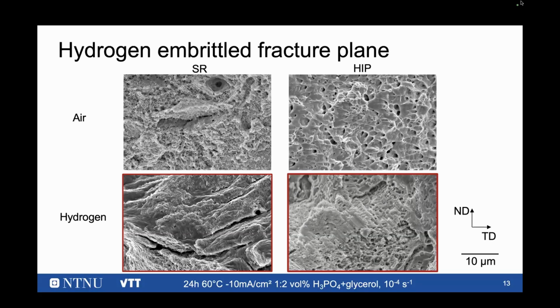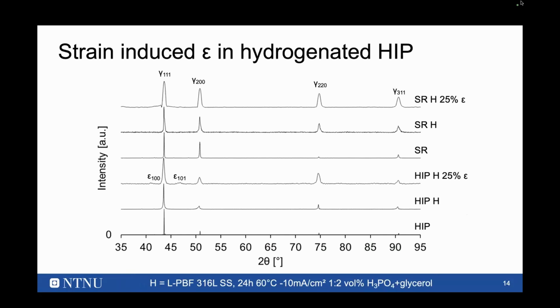We see the voids present in the air condition. The void size can be related, in the stress relieved condition, to the dislocation cell size that we saw earlier. So that's why the void size in SR is lower than in HIP. And then when we go to the hydrogen condition, we got more brittle features with some quasi-cleavage features in both cases. So it looks quite different. There was something else causing this difference in the effect.